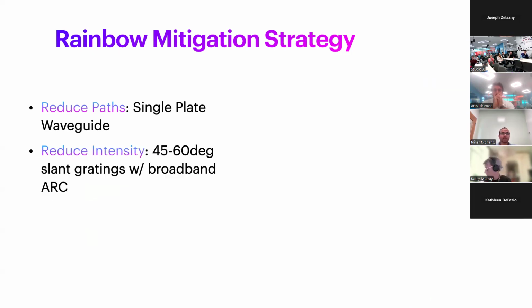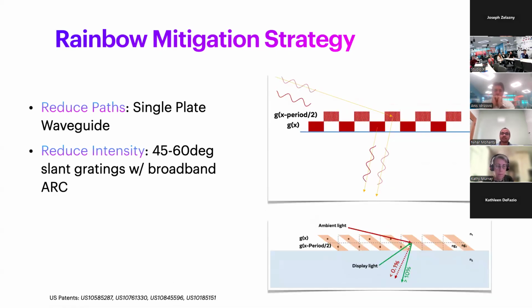Now that you have a single plate waveguide, the second key path to reduce the rainbow is to reduce the rainbow intensity. The key challenge here is to reduce the rainbow while not impacting the display path, as they both share similar paths. Analogous to the principles of active noise cancelling, whereby using destructive interference between two signals the noise signal can be cancelled, we discovered similar phenomena with deep gratings at 45 to 60 degree slant, which at optimum thickness can reduce some of the rainbow paths through destructive interference with minimal impact on the display path.